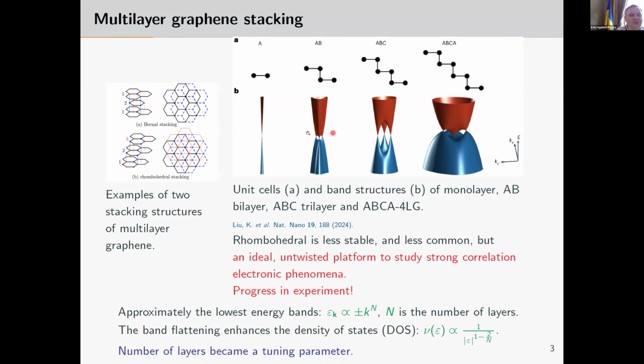And here are examples of band calculations for one K point. The first one is just monolayer graphene, then bilayer graphene, and three-layer graphene, and so on. The features which develop here are caused by the so-called trigonal warping effects. It's rhombohedral graphene. The problem with the system is that it's less common, and thermodynamically it's less stable.